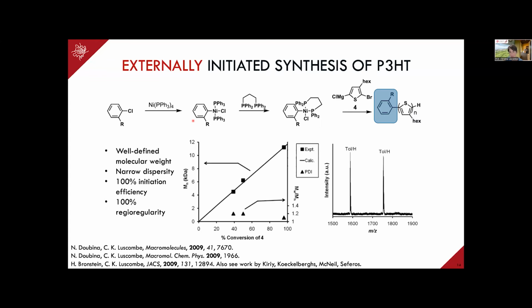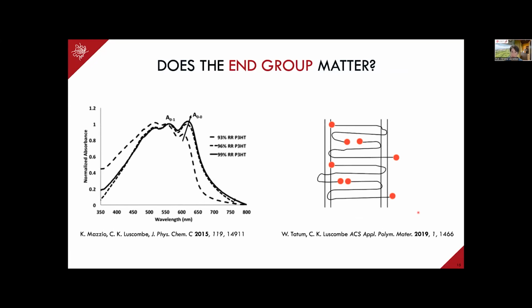Looking at other aspects of this as well. So one of the things that I highlighted is, well, we can introduce different types of end groups. And the question is, well, do these end groups really matter? And in this study that I'm showing on the right, we showed that the end group does really matter. So if you could imagine the crystalline domain of your polymer, you'll have a polymer chain folding back and forth and back and forth. End groups do end up in the crystalline region, and the end groups act as defects in the crystal. But if the end groups are more similar to the backbone, so for example, if the end group is an aromatic group, then it disrupts this crystal less, and so we end up with greater performance by controlling the end group.